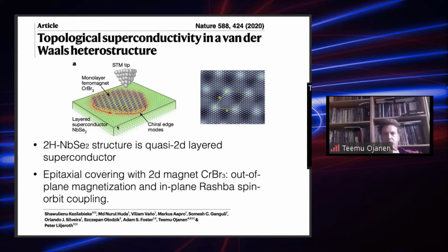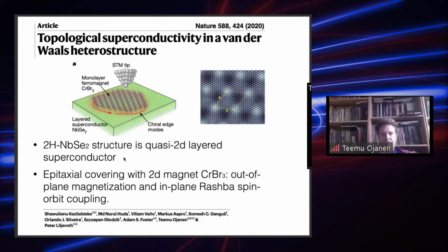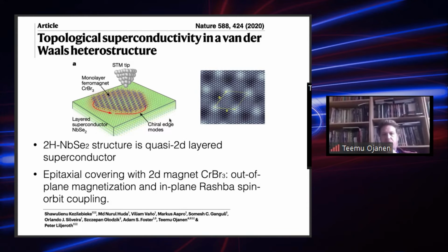So the experimental groups managed to grow epitaxially a monolayer chromium tribromide on top of a 2H niobium diselenide, which is a layered superconductor. So this is a 3D superconductor, but actually it consists of 2D layers, which are in some sense extremely weakly coupled layers. Right. And the experimental tour de force in the sample fabrication was that Shavolin managed to somehow grow epitaxially this 2D, or believed to be 2D ferromagnet chromium tribromide on top of 2H niobium diselenide.